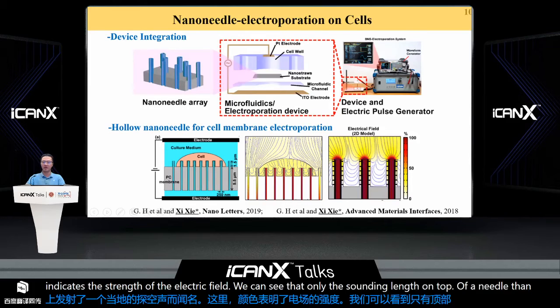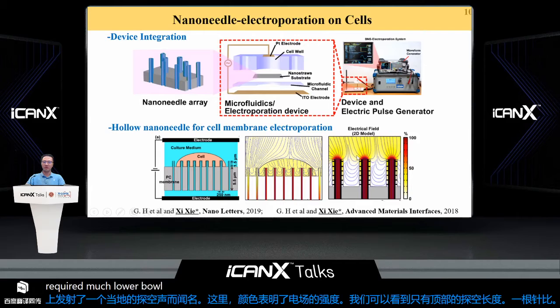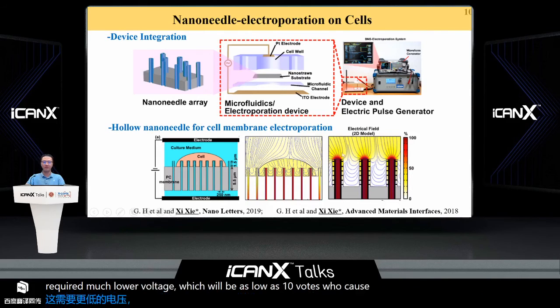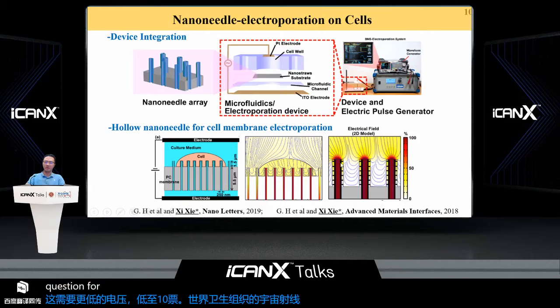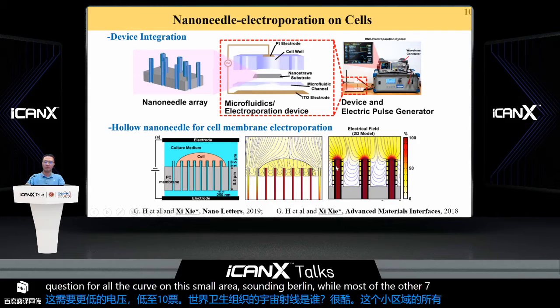experience a high electrical field. This requires much lower voltage, which could be as low as 10 volts, to cause membrane poration. Therefore, electroporation could preferably occur on this small area of the cell membrane, while most of the other cell membrane could remain intact.